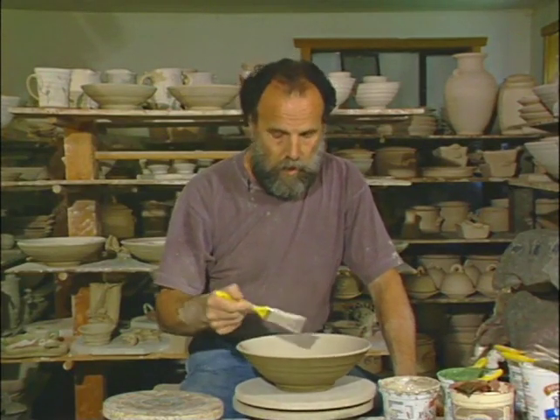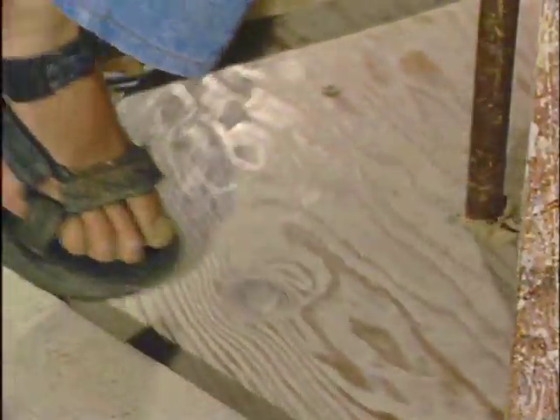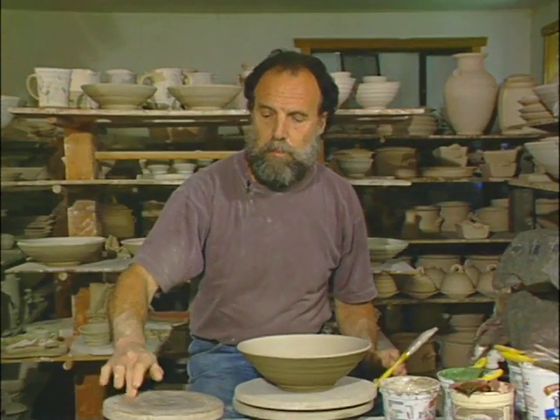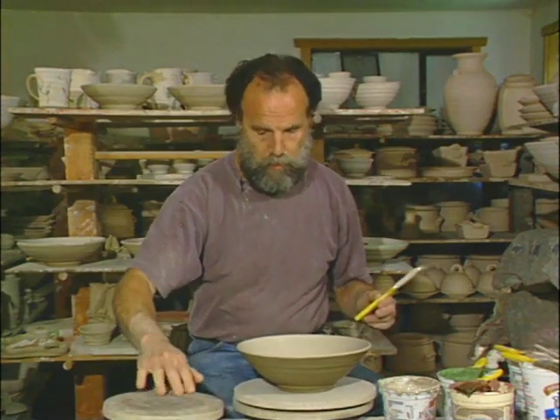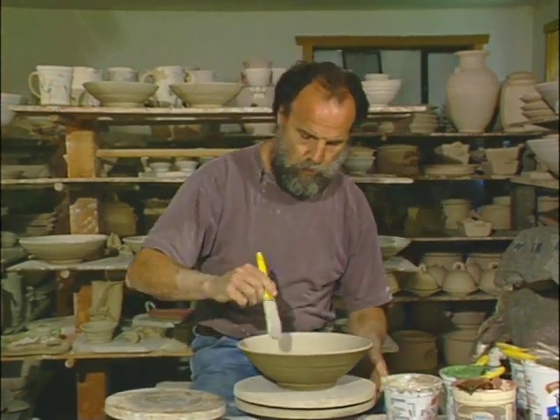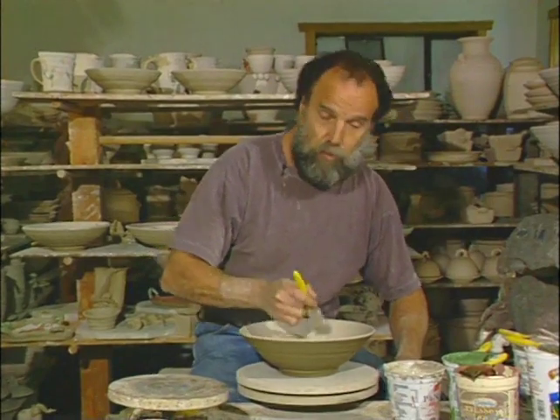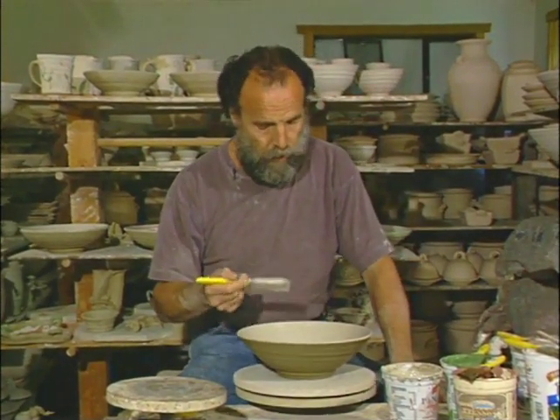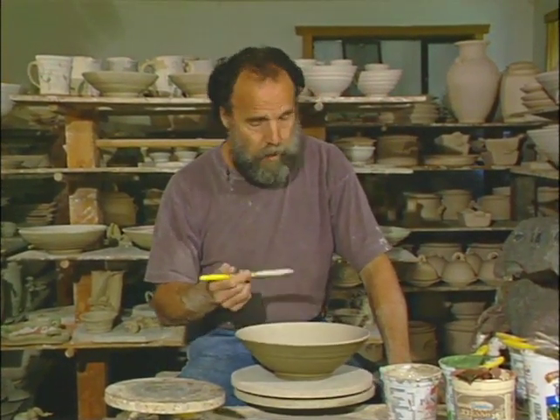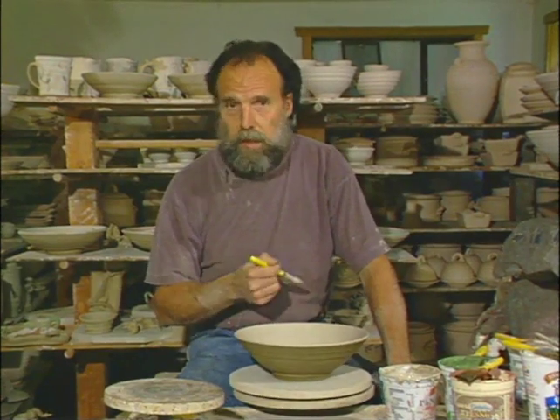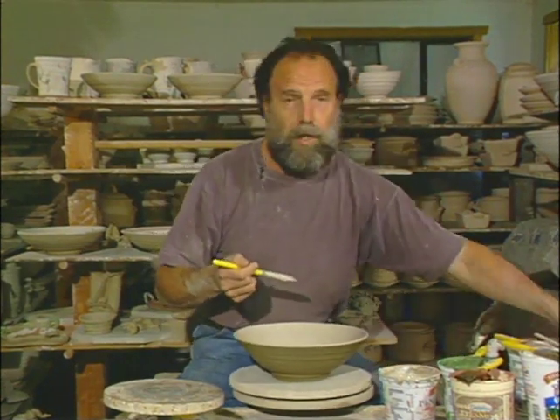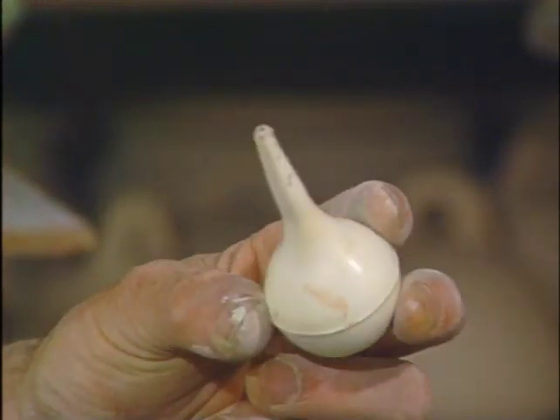I'm using a kick wheel to apply the slip to the pot, but it's quite convenient also to use a banding wheel to keep the pot turning while you apply the slip to it with a brush. It's possible also to apply slips to pots by pouring it, by dipping the pots into the slip, or in fact trailing it with some sort of a syringe like this.